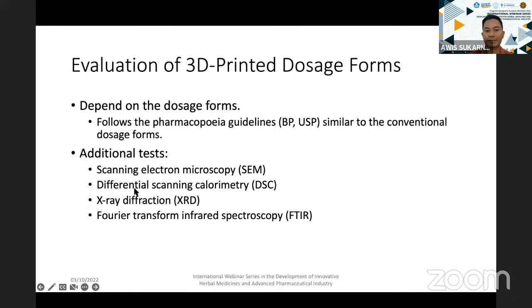And then the next one is DSC, or differential scanning calorimetry. This one is especially useful if you use the hot melt extrusion technique, because sometimes when you mix it together, the drug changes. I showed you one of the results from a study done by another researcher. At the beginning, the drug may have a melting point, but after you run it using the hot melt extrusion technique, the melting point disappears and it becomes a glass transition temperature. So it means the drug or the active ingredient changes its properties from crystalline to amorphous.